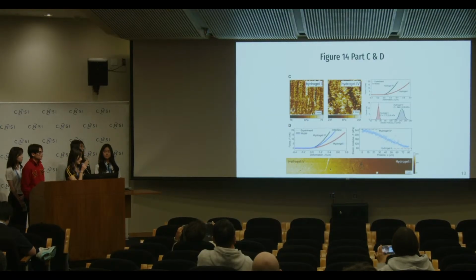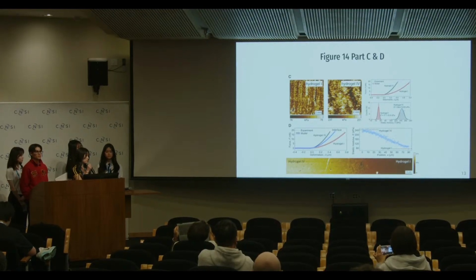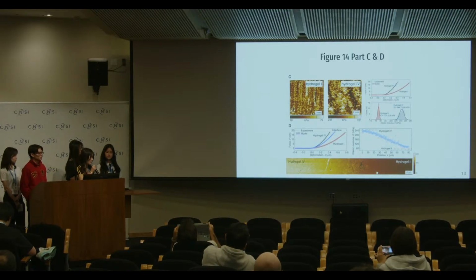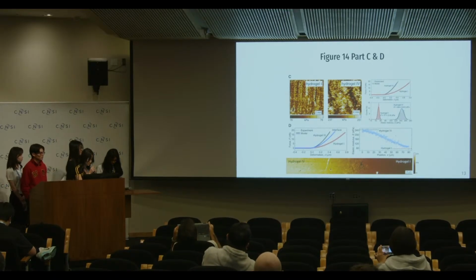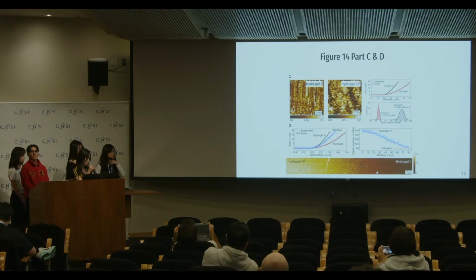So part C and D of figure 14 focuses on AFM mechanical mapping of the two different hydrogels named hydrogel 1 and hydrogel 4. Hydrogel 1 on the left has a lower stiffness range, while hydrogel 4 on the right has a much higher stiffness. These images show how stiff different regions of the hydrogel are, spatially resolved. On the top right, these graphs compare force deformation curves for hydrogel 1 and 4. According to the graph, hydrogel 4 resists deformation more, confirming its higher stiffness. Part D reinforces that hydrogel 4 is over 3 times stiffer than hydrogel 1.